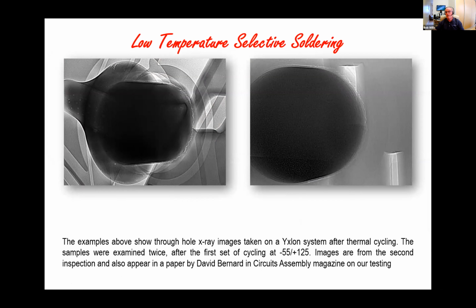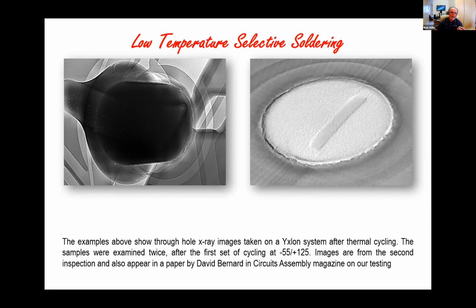We can also use X-ray, and in this example, I took those sample boards and we X-rayed them. And if you look around the barrel of the hole, that's the large black area on this X-ray image, you can actually see some evidence of cracking around the barrel and between the barrel and the pad. So again, the techniques we have on our shop floor today will allow us to still analyze and look at joints with the tin bismuth materials, which is fairly well understood. But sometimes when you use something different, people wonder whether or not it's going to be an issue or not.